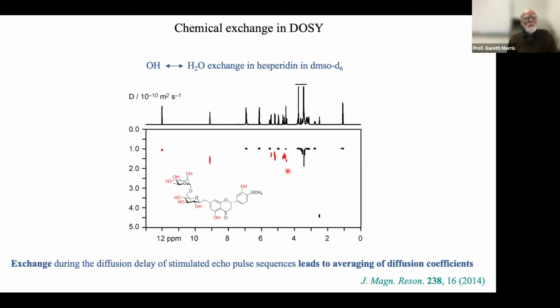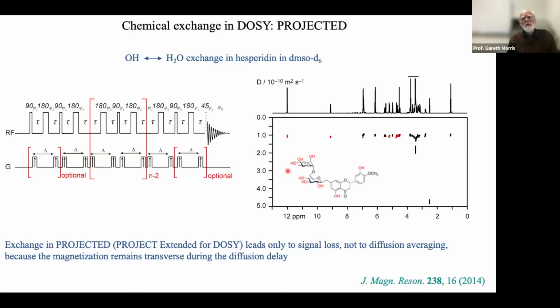We can get around it if we need to by choosing an experiment in which, instead of encoding our magnetization with position and then storing it as Z magnetization, we leave it as transverse magnetization. And that means that if we have chemical exchange, we'll get dephasing and loss of the exchanging signals. And so exchange causes signal attenuation instead of change in diffusional attenuation. And so here in this particular experiment, our OHs line up again.